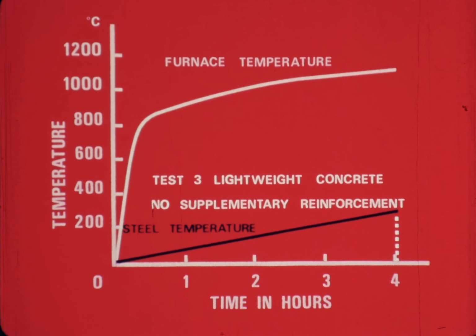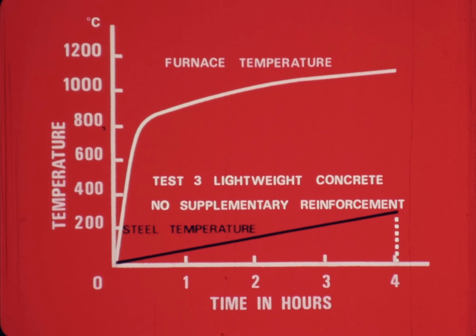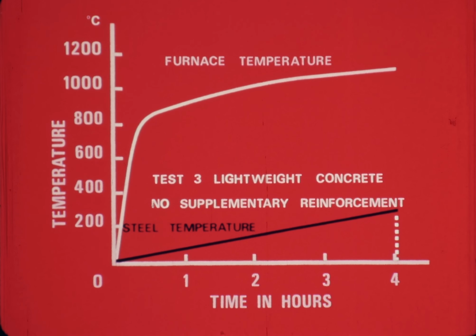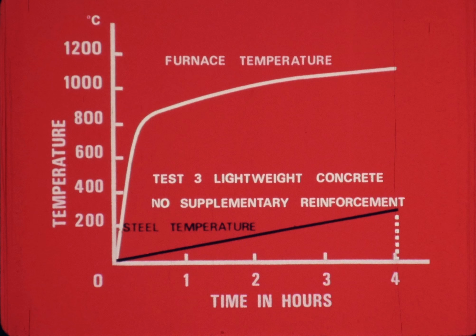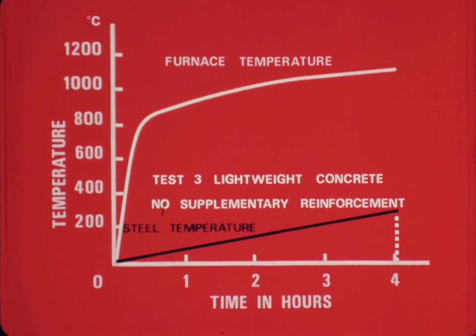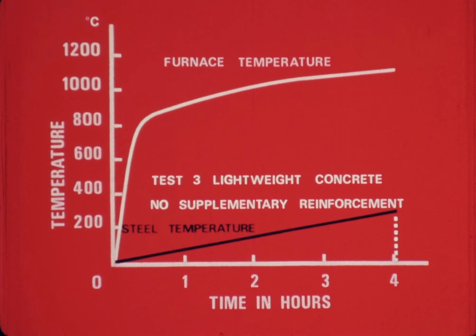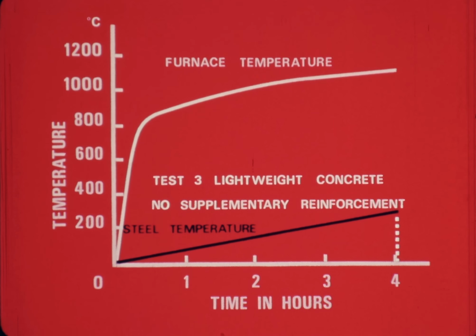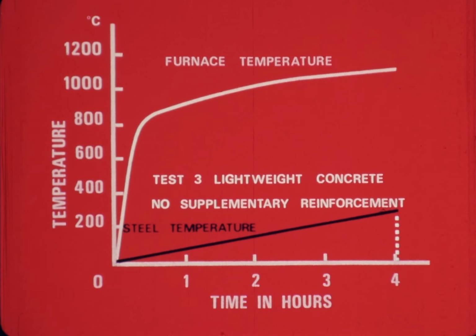The third test showed that the use of fire-resisting lightweight aggregate provided still better protection. The steel temperature rose even more slowly. After 2 hours, it reached only 150, and after 4 hours, only 280 degrees. Again, the beam satisfactorily withstood the test.